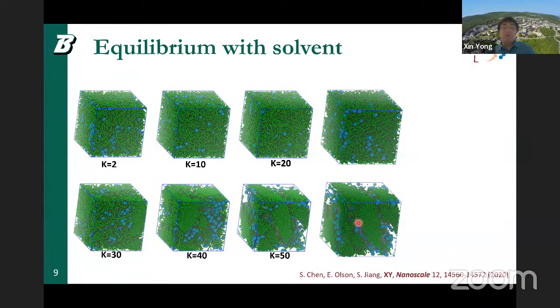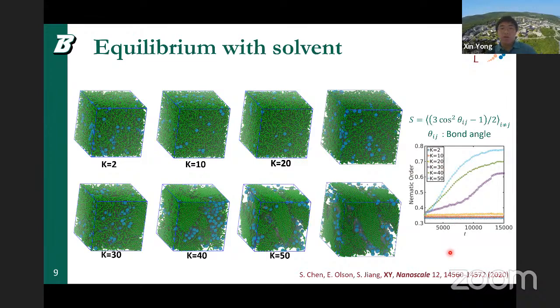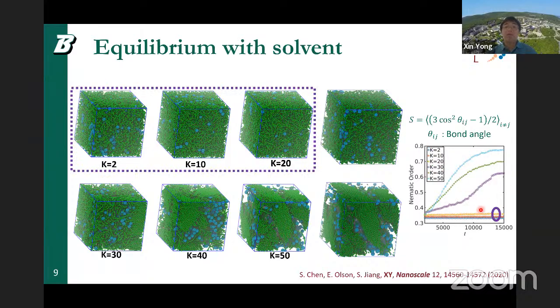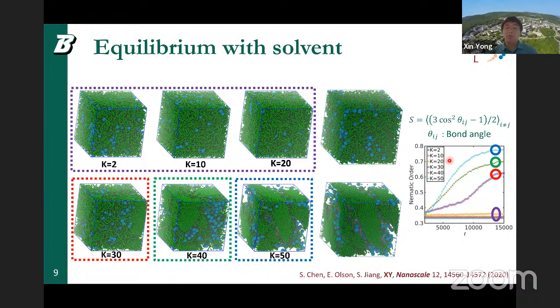So what we see here is that the rigidity of the polymer will actually influence its assembly, so that it's not homogeneous anymore. You have some kind of microphase separation, and the particles start to only sit in those voids. And when we characterize the nematic ordering parameters for the polymer systems, as we can see here, by varying K, at first you don't see much change. That means the systems are highly homogeneous and random. As you start to increase K over 30, you start to see the development of nematic ordering. And this gets increasing in time as well as increasing in K.